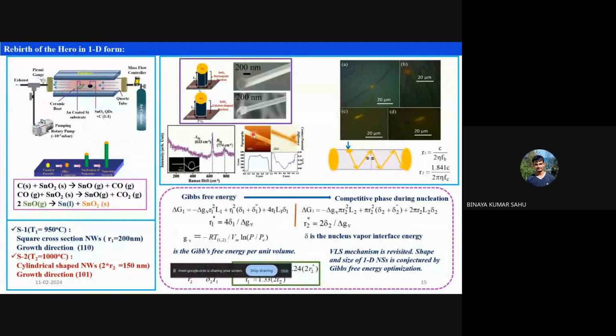And as I was claiming the surface smoothness and all, we also did a few AFM, and this is a very special technique known as KPFM, Kelvin probe force microscopy. Again, I will not go into detail. From there, you can see the surface potential of that material, and it is also very much uniform.